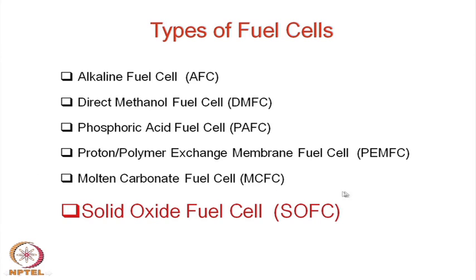Then there is another type of fuel cell where the electrolyte is once again liquid, but at a sufficiently higher temperature, fairly high temperature, about 600 to 800 degrees centigrade. So, this is a liquid carbonate, and the carbonate ion is the charge carrying species, and this is a moderate temperature fuel cell where molten carbonates are normally used as the electrolyte. The operating temperatures of these are different. This is more or less room temperature. These are again slightly above room temperature. I will give you some temperature range, but they operate at different temperature ranges.